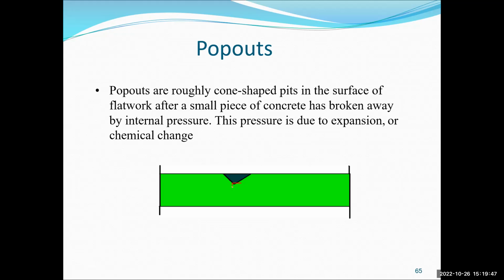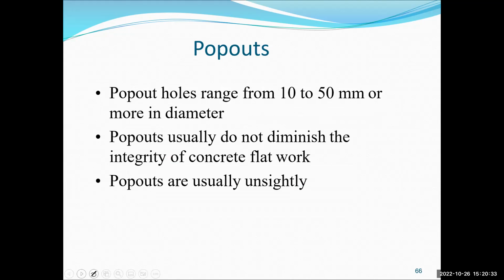Now, pop out is not really unhealthy, but it is unsightly because of internal pressure. What happens is that there will be aggregate here. The main cause of it is alkali aggregate. This alkali aggregate reactivity will cause some kind of internal pressure, especially whether we have aggregate here or reinforcing bars too close to the surface. If the concrete cover is very thin, then because of the steel reinforcing bars contracting and expanding, this will cause some kind of pop out. So this pressure is due to expansion or chemical change, either due to the aggregate itself or the expansion and contraction of reinforcing bar in the concrete. Usually, for pop outs between half an inch to 2 inches, they do not really diminish the value or the concrete strength, but they are unsightly.